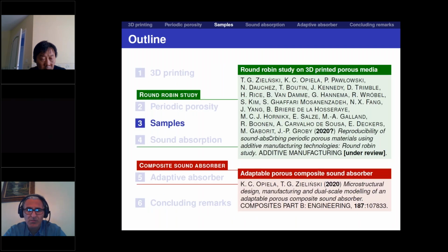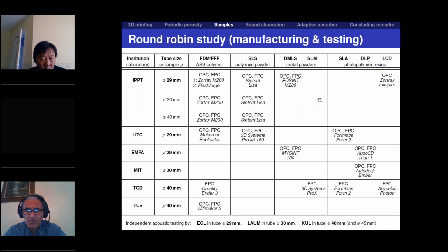Many laboratories did it. Actually, there were 9 institutions involved, but 6 laboratories actually manufactured their samples and measured them in the impedance tubes. But I also invited 3 additional laboratories to check the results of the acoustical testing. I'm going to show you only the results for the samples with the diameter of 29 millimeters, so the results from IPPT from Poland, from Université de Technologie de Compiègne from France, and from EMPA from Switzerland. You see that all the technologies are involved. There were a lot of 3D printers that were used to manufacture the samples. For example, at my institution, we used even 2 different printers for FDM technology.